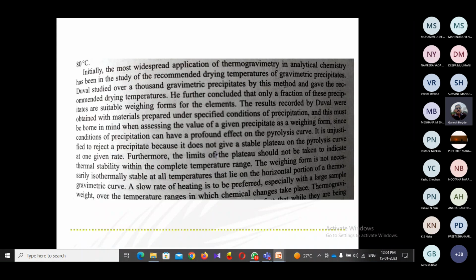If you have a prepared tablet or a particular composition, the TG of that one is studied, the temperature is increased to a certain level, and then material stability is checked. That is actually calibrated. If the material is stable at a certain higher temperature for a certain period of time, that is equivalent to a certain number of years. That standardization is usually done, and based on the material stability in the thermogravimetric curve, its expiry date can be evaluated. So this is one of the very interesting applications of TG in pharmaceutical analysis.